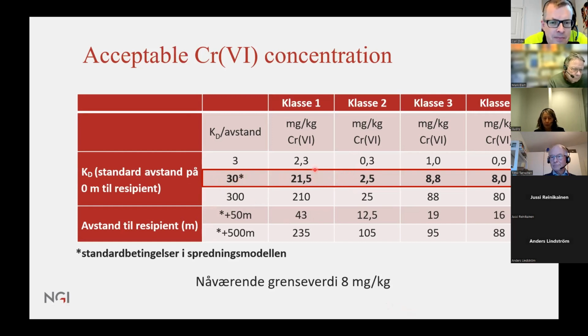Then we get these values for these different scenarios. So we see for the road construction, this is lower than the current 8 milligram per kilogram using default values. But if we reduce the KD to 3, which is a very low KD value for chromium 6, but let's say that's an extreme situation, we see that all these 3 classes will be lower compared to the guideline, which is the guideline for the free use of waste concrete in Norway. But if the distance is increasing, or the KD is increasing, and also the distance to the recipient, the guideline value or the acceptance criteria are also increasing.